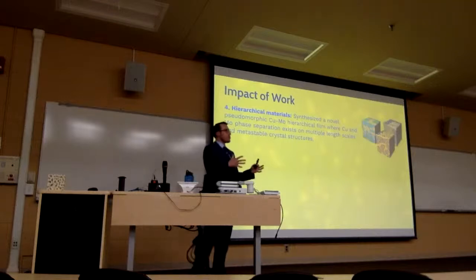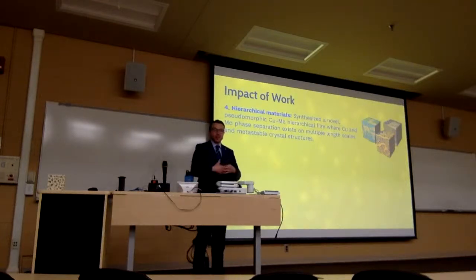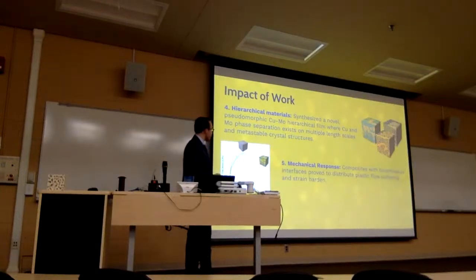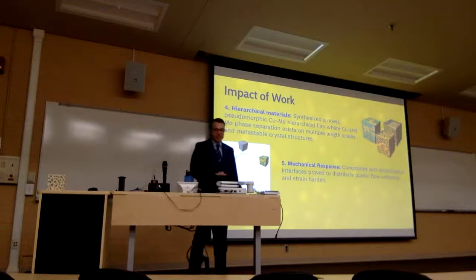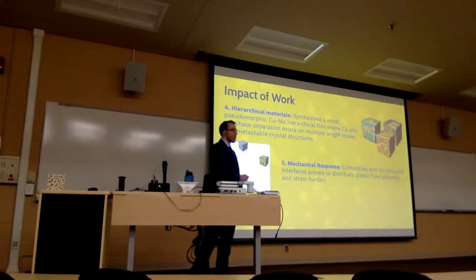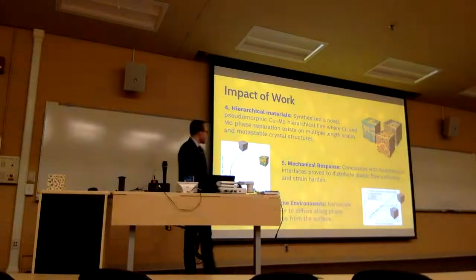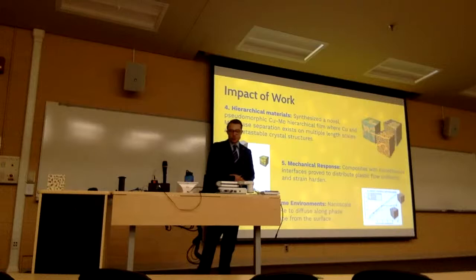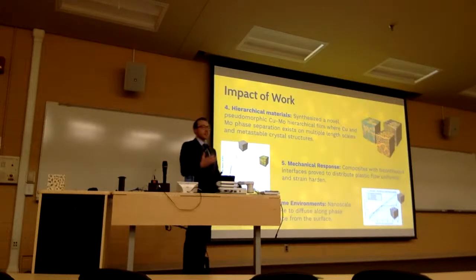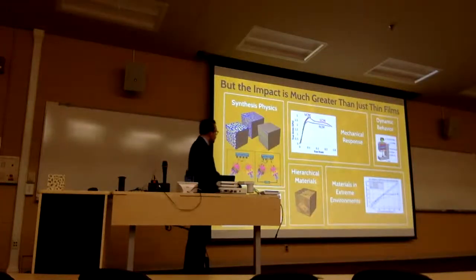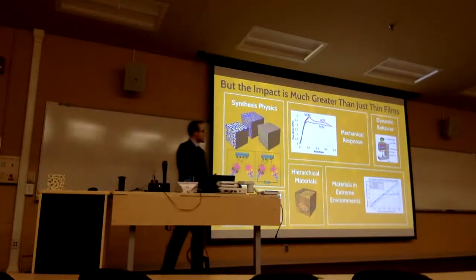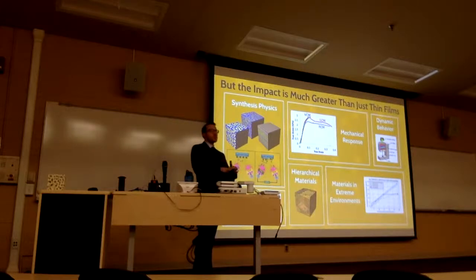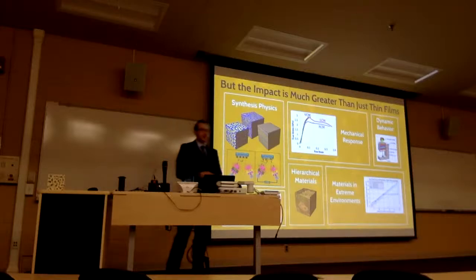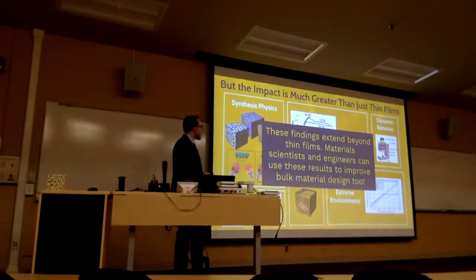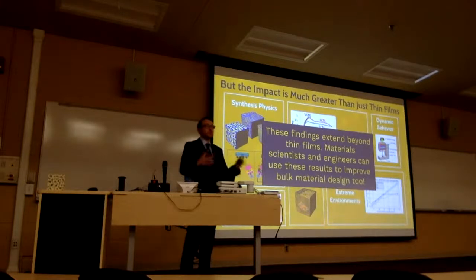We designed these hierarchical novel materials where we have phase separation happening at different length scales in the sample. We tested the mechanical response by deforming these samples inside the TEM and seeing how they behave, and they deform much more uniformly. And we experimented with implanting these samples and exposing them to irradiation and seeing how they retain helium inside the sample. So we did a whole slew of different experiments in this work, but I'd like to stress that the impact of this work goes much beyond just thin film design. It can actually impact materials design across material science. We can actually use these results in bulk materials to improve the design of materials and improve their performance in various applications.